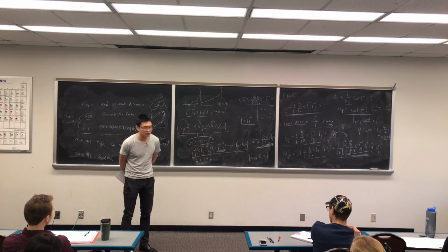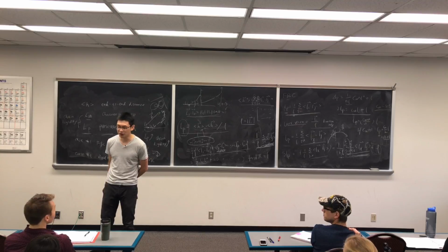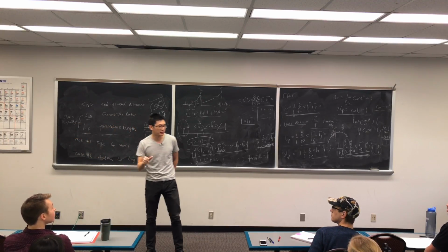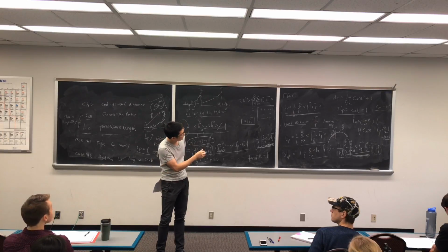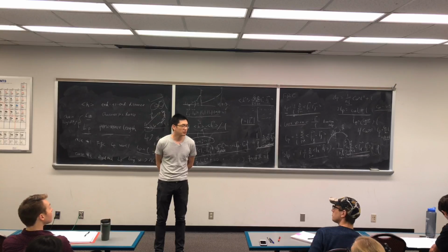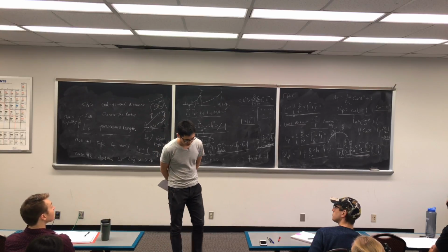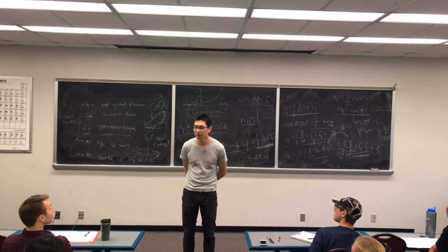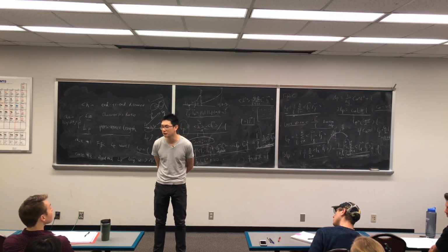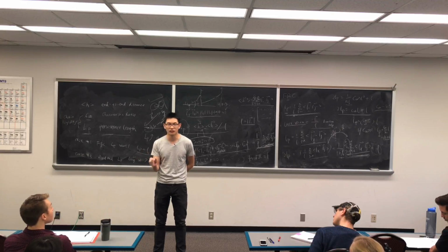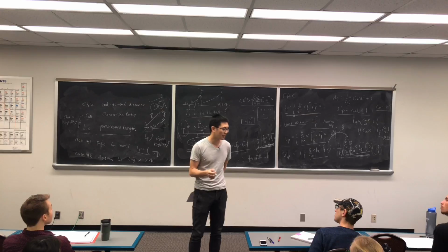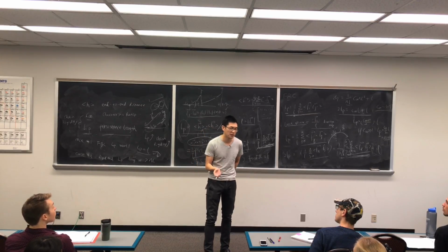In some more extreme cases, your chain can be relatively rigid, when C infinity or LP is much larger than 1 nanometer. I'll give you a few examples of rigid rod-like polymers. Polyimide, or any polymer with liquid crystalline properties, where they have a lot of double bonds in the backbone direction, can have persistence lengths up to hundreds of nanometers or 1 micron.